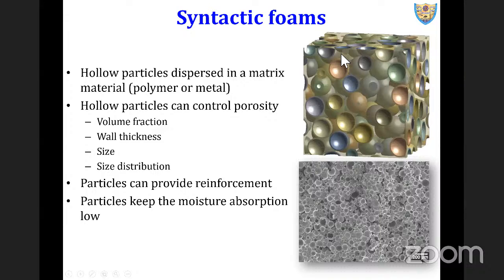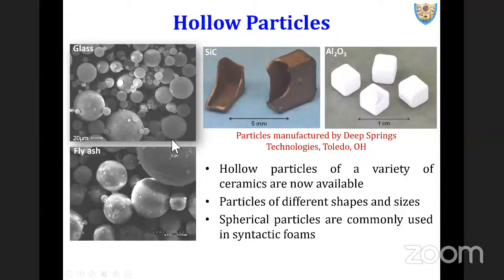So here typically these microballoons are in the particle shape. Those are spherical in nature. Many particles are available. Glass are engineered ones, and those are commercially available. Fly ash cenospheres are naturally burnt ones, which are the environmental pollutants. So from the fly ash, you can extract the hollow particles known as cenospheres and utilize them. So these are naturally abundantly available, which are environmental pollutant ones. So you can find and utilize it in components, products out of them. Engineered ones are available by many companies.